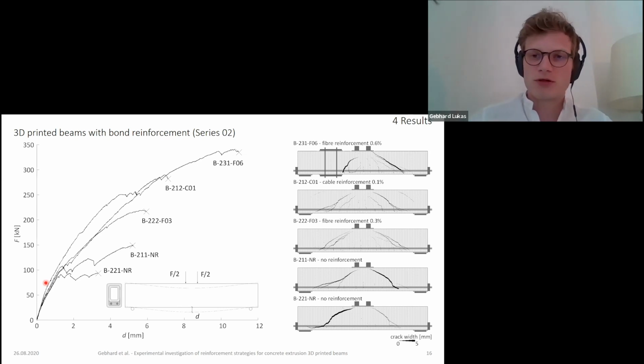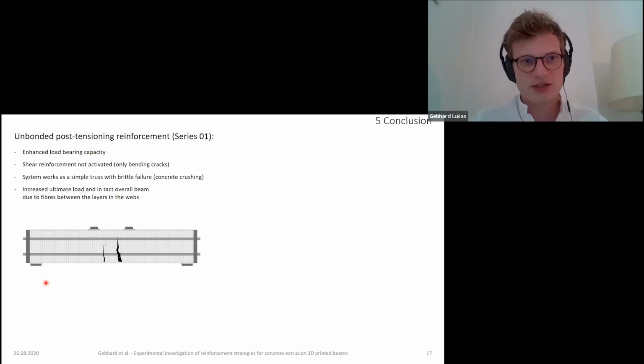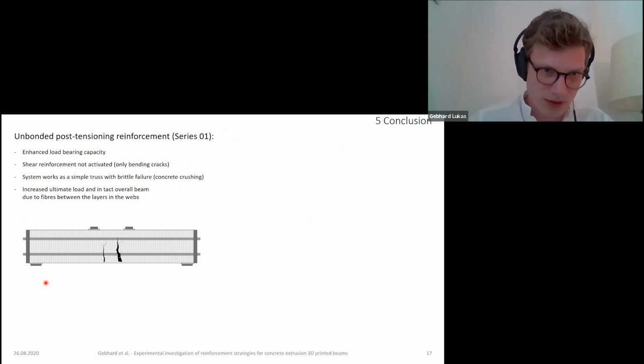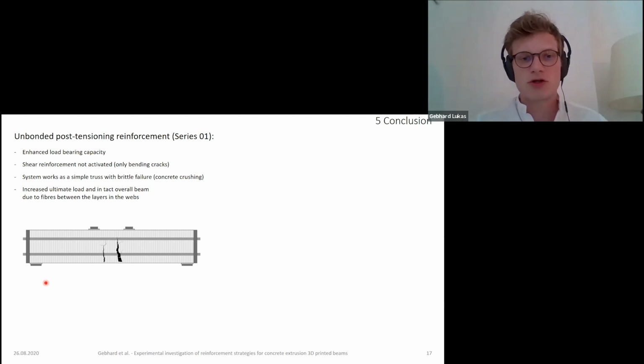So what could we learn from this experimental study? Here you see, as an example, a beam of series 1, where we had an enhanced load bearing capacity due to the post-tensioning, as you would expect. However, we only developed bending cracks since the reinforcement was unbonded and the shear reinforcement was not activated. So we had a simple truss with a highly brittle failure. And when fibers were present, the ultimate load could be increased and the overall beam stayed intact.